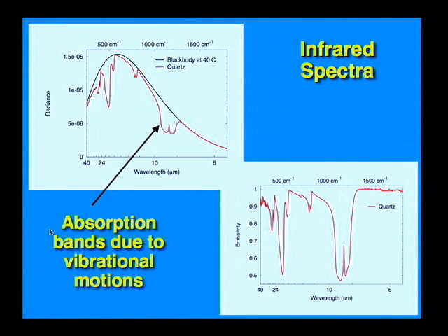Okay, so to quickly come back to our vibrational model, what's happening is, if I can explain this quickly and simply, deep inside the material, I've got all these motions, and it's generating this Planck-like distribution of energy. As that energy tries to escape from that crystal, it's being preferentially absorbed at frequencies or wavelengths that correspond to these harmonic frequencies. Okay, so this particular frequency that corresponds to a wavelength of, say, 20 microns, that's one of these harmonic frequencies. So the energy that's trying to get out is preferentially absorbed.